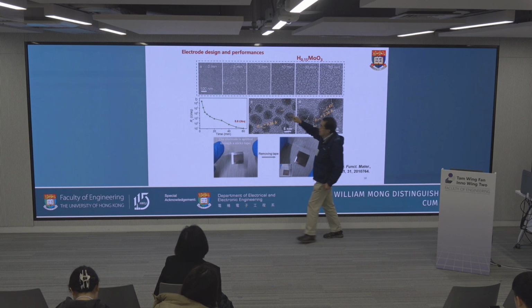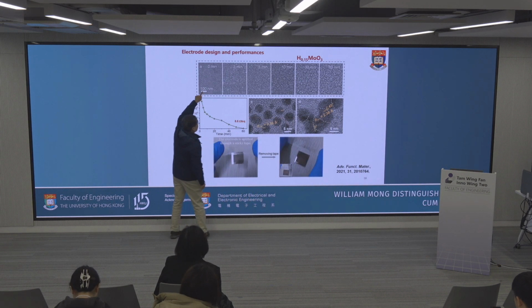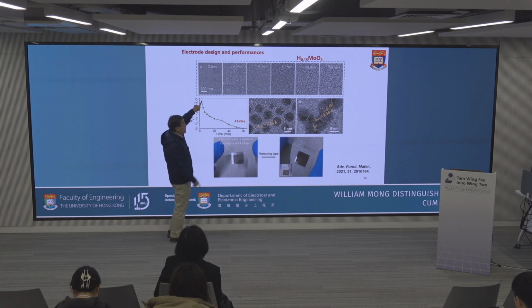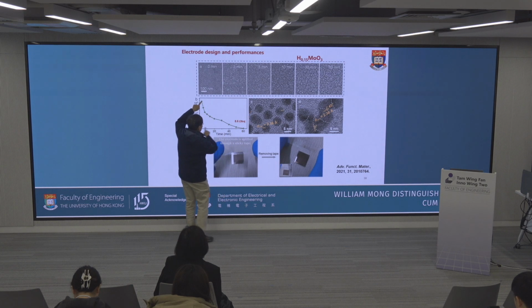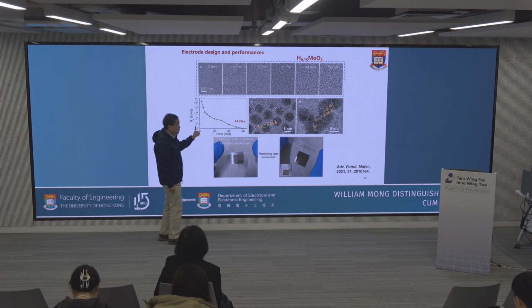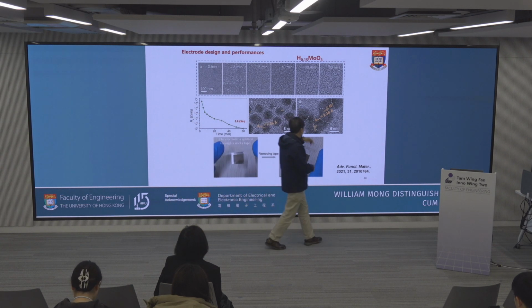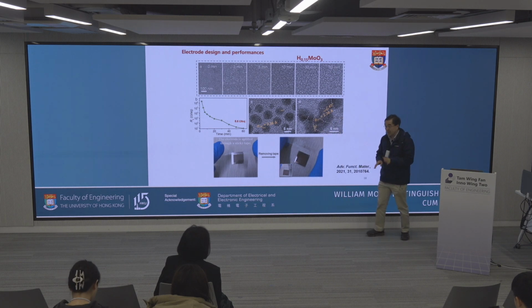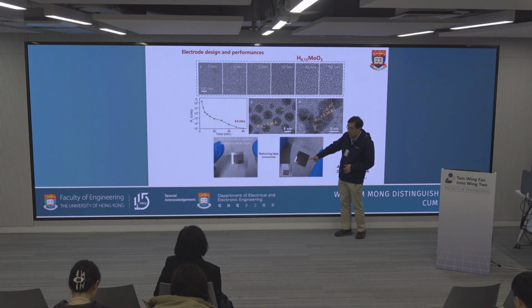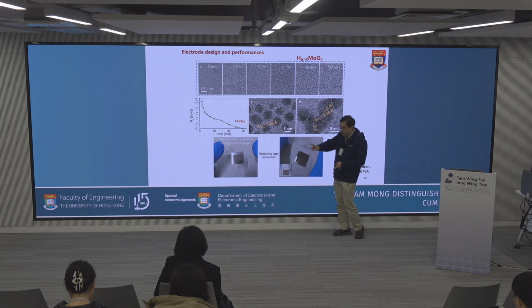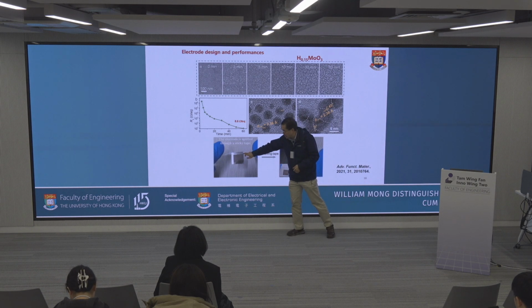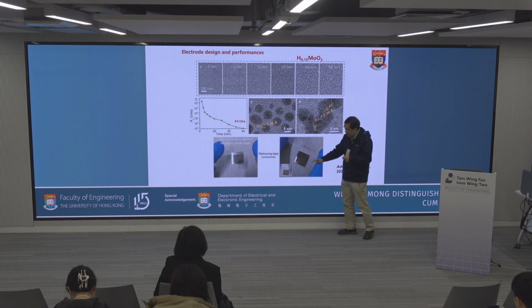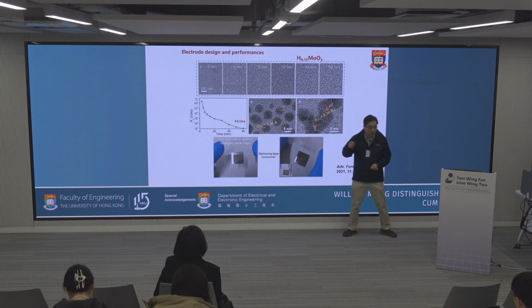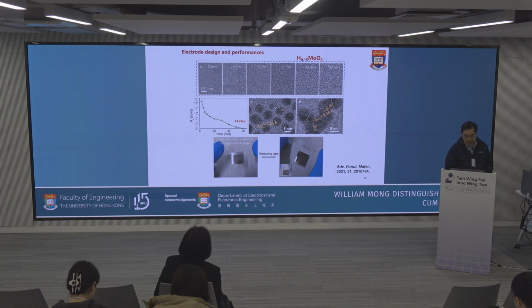At the beginning the particles are not sintered, and the resistance is very high. After sintering, they become clusters and the conductivity is very good, as good as what we can get in evaporated electrodes. We form it by solution process at room temperature. But you ask, is this stable? We scratch it, and peel it off with a tape stuck on the electrode. We cannot peel off the electrode, which means it bonds quite strongly to the device without damaging the device.